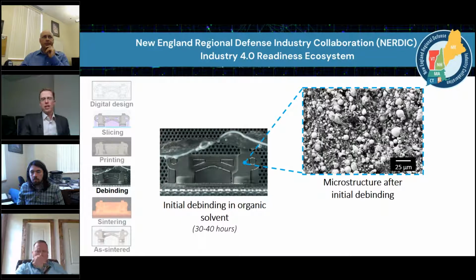If we look at a part after it's been debound, everywhere where there's black, it's this polymer that we're seeing, and all these white spheres are the metal powder. So you see that there's quite a range in powder size, some relatively large like up here, and then lots of relatively small powder sizes. This powder size is different than what you're going to find in powder bed fusion.